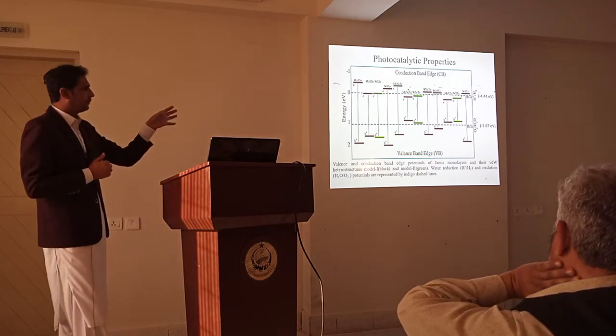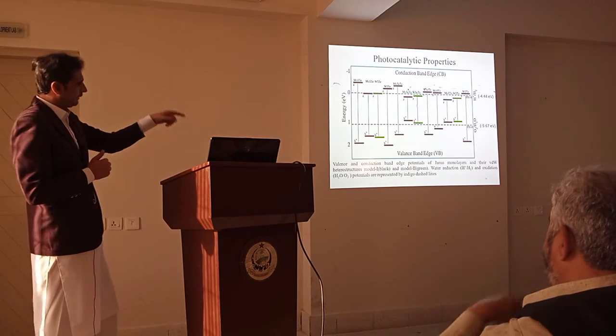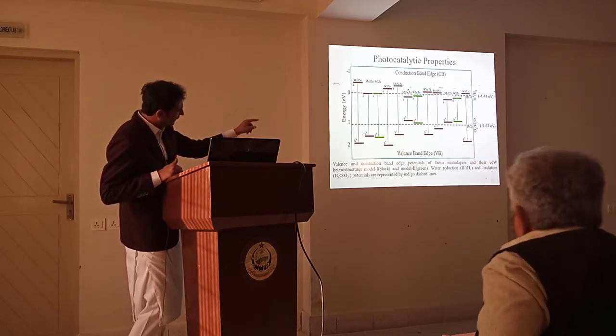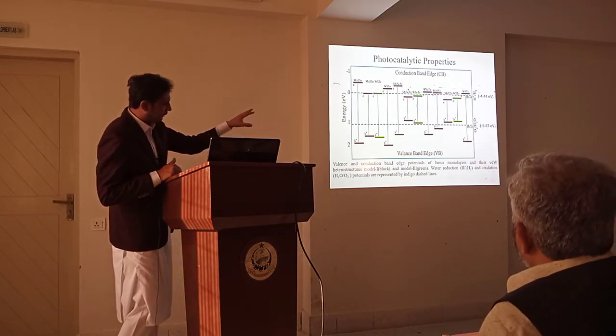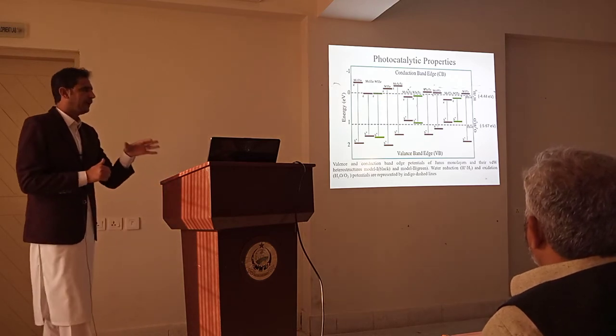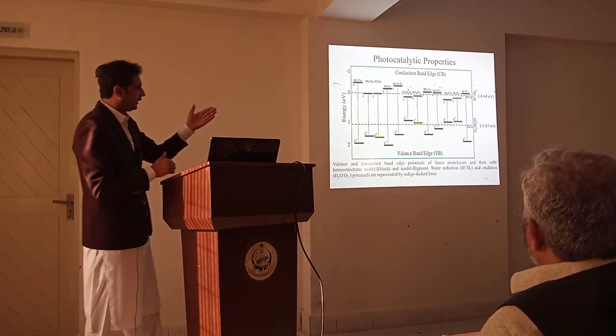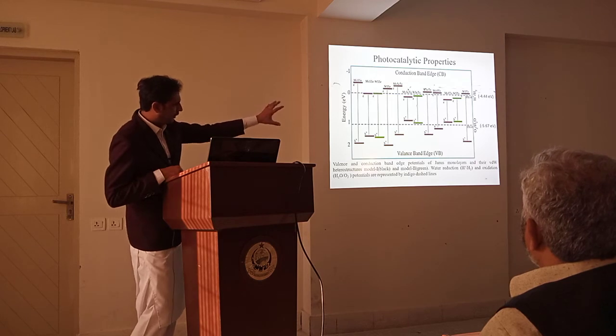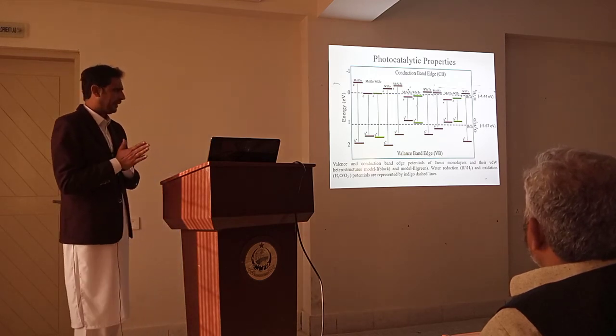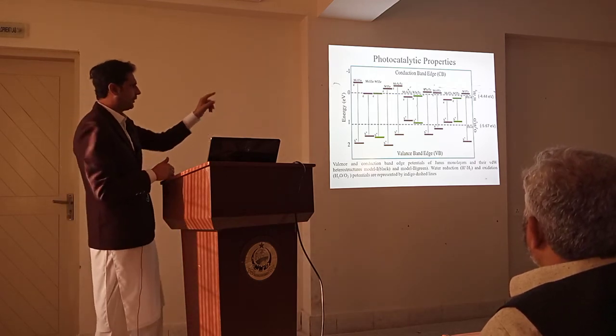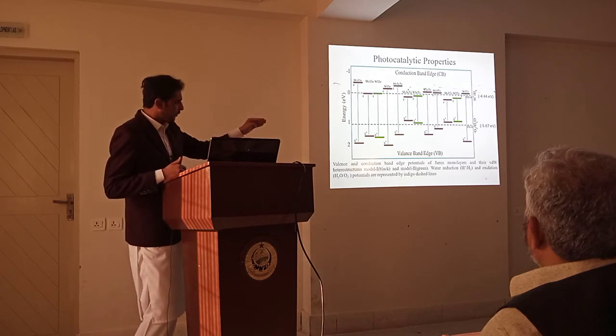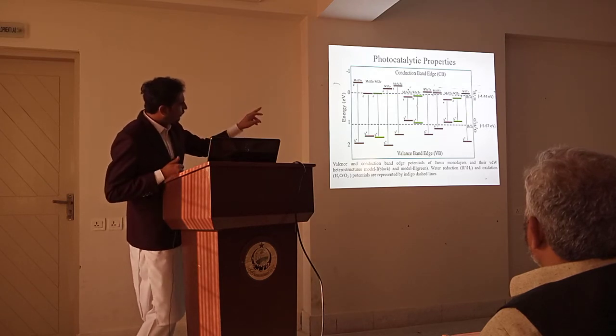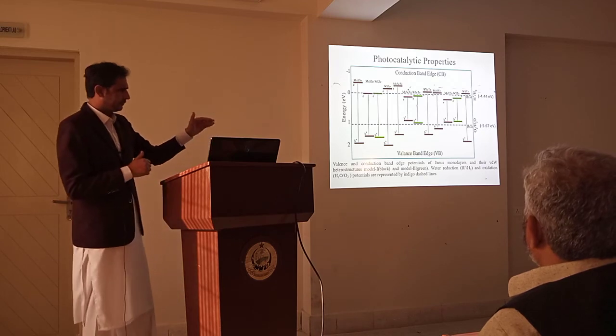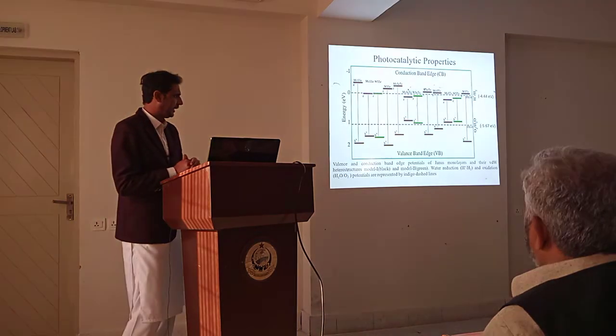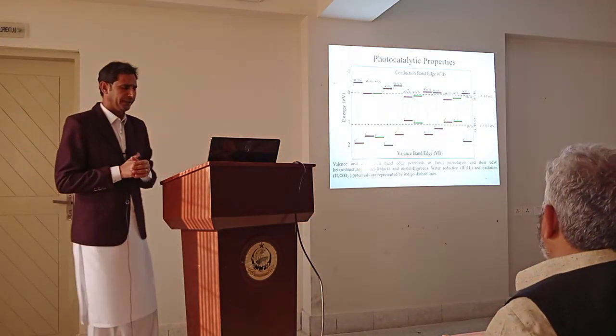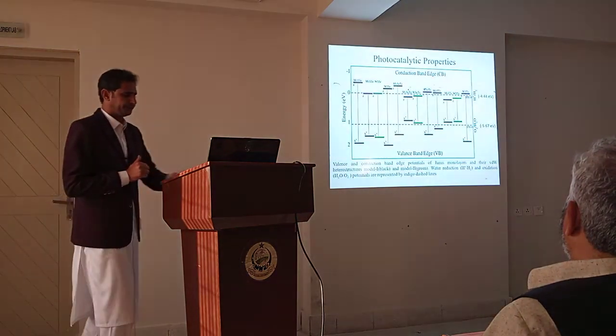Here we can see all the monolayers. For example, for MoSSe, we can see that MoSSe crosses the redox potentials. It means that this material is best for water splitting. Similarly, for WSSe, these monolayers are best for water splitting. While in the case of the heterostructures, for MoSSe and WSSe, only the oxidation line is crossed. It means that these materials are only good for oxidation, while they fail for reduction.